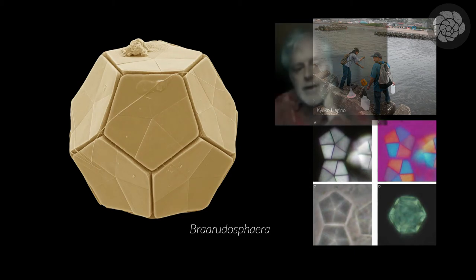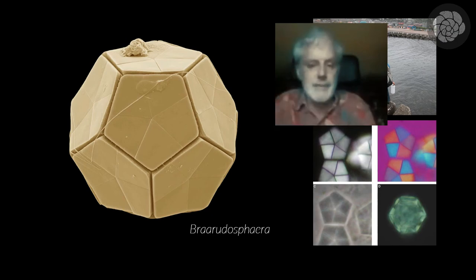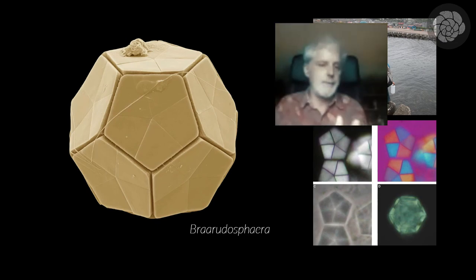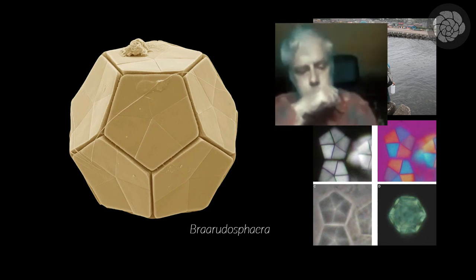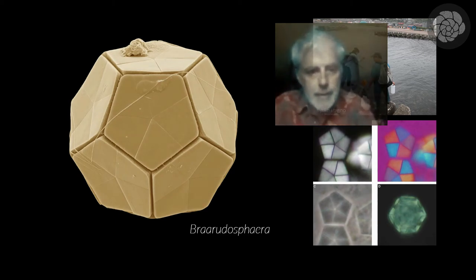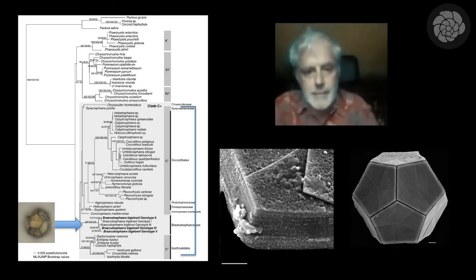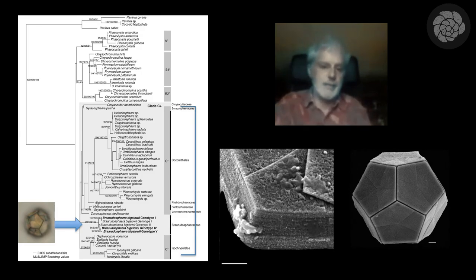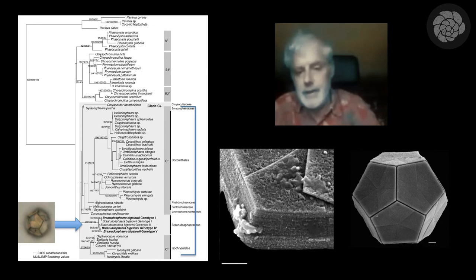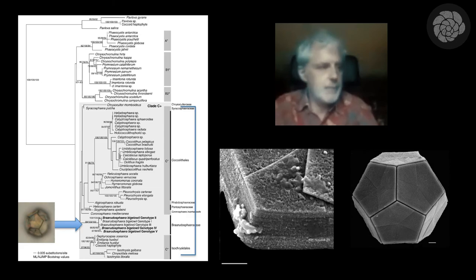And we know from beautiful work, particularly by Kyoko Hagino, that they're definitely not heterococcoliths. We know the alternate life cycle phase in this case is a haptophyte which doesn't calcify. The calcification occurs around the outside of the cell, they don't form inside the cell and exocytose. In terms of the biomineralization, they're very different. They've got tangential calcite C axes rather than radial, and these five units each behave as a single crystal unit with a tangential C-axis. If we look at them in side view, they've got a laminar substructure, formed of fine little laminae, and they seem to grow by stacking up laminae. So they're growing in a very different way to either heterococcoliths or holococcoliths. So again, that's a different biomineralization mode, which seems to have evolved separately.